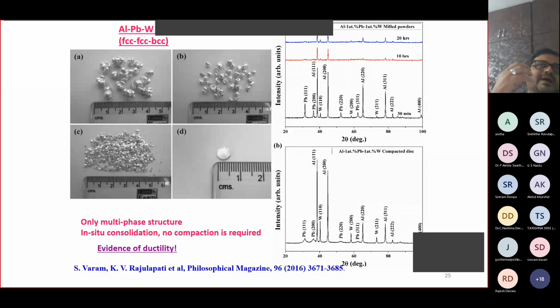So now we have seen what happens when you add lead to aluminum and make it nanostructured. We also have seen what happens to aluminum when you add tungsten to it. But now if we add both tungsten and lead in small quantities simultaneously, what happens? We did not get powders, but we got chunks like this, and we still have a multi-phase structure, and it remained intact. And the best part here is that everything got compacted during milling itself, so you don't need to compact those powders using high temperature or external pressure. And that shows that this sample is kind of ductile.